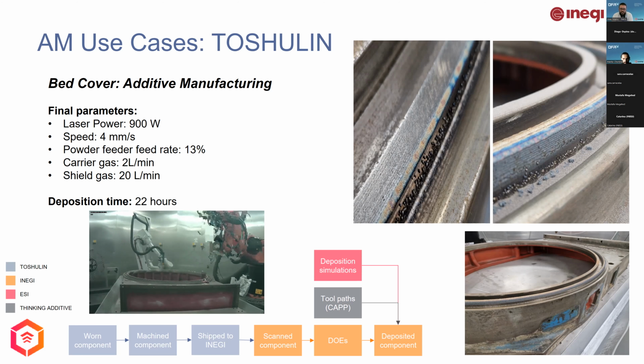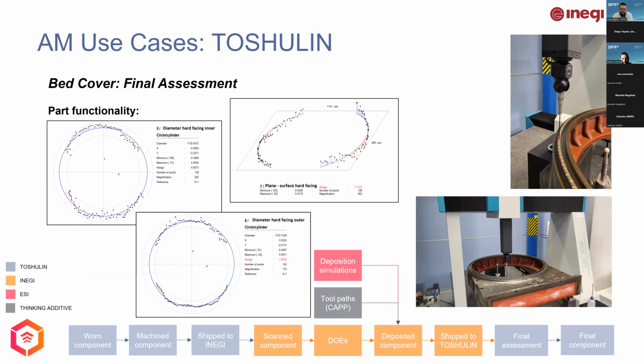After this, the part was shipped to Toshulin for assessment of the final result. The first assessment was of the part functionality. The part was measured for geometrical deviations. Based on those results, it was stated that the part after repair is fully usable without the need for further machining of the added material. The dimensions and shape of the repaired area comply with the requirements set by Toshulin.